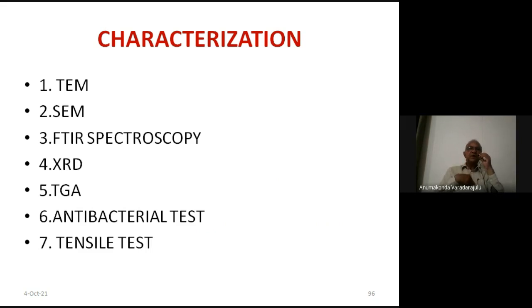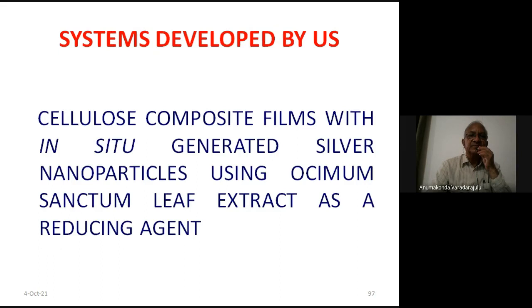After that, we have to characterize. We use the techniques TEM, SEM, FTIR spectroscopy to study the interactions between the metal nanoparticle and the matrix. The XRD to prove the nature of this nano metal. Then TGA to see the thermal stability, antibacterial test, and then tensile strength test for some systems and so on.